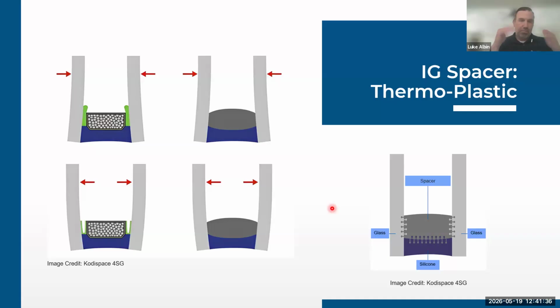And again, when we're taking a look at our climate zone, that thermal expansion and contraction is happening with not only the window frame itself and the interaction between that and the IGU, but also the IGU itself. As that flexes in and out with thermal expansion and contraction, the thermoplastic spacer moves with the glass. I'm sure everybody has had the experience of seeing a window that looks like it's raining in between the panes. That seal is broken. Any gas that was in it has probably dissipated long ago. Condensation is building up on the inside, but that seal has failed. So as you can imagine, a metal IG spacer bar is not going to flex with it, and that's typically where the seal failures happen.